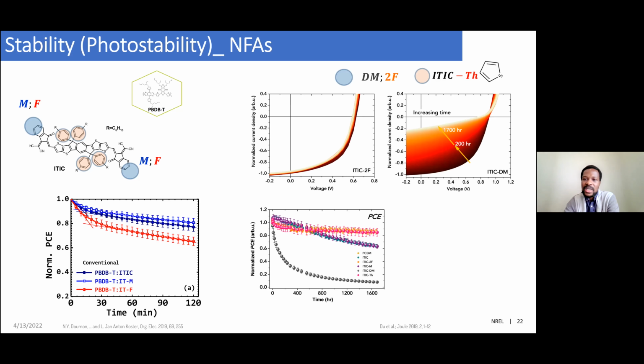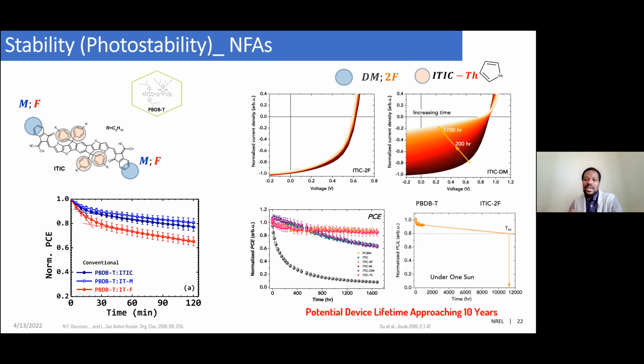And they also prove that when you double the methyl group, which becomes the worst performance here, you also lose a lot in terms of the fill factor. But one good thing is that with the 2F, you have a better stability. The fill factor does not change that much. And with their result, they're able to predict a 10-year lifetime for this type of device, PBDBT. So the same polymer combined with ITIC2F can give you a better result, which is also good news compared to what we have done.